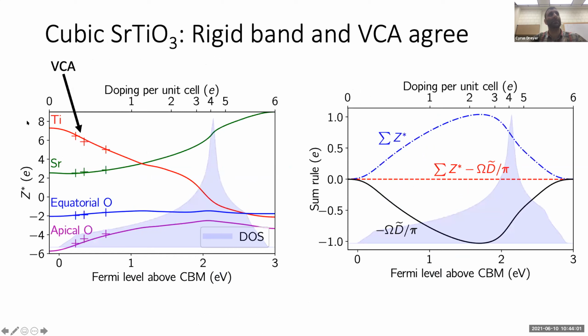So this is the same plot I showed for tin sulfide, Born effective charge versus Fermi level. Here we're doping across the entire T2G band. Of course, in an experiment this would be completely impossible, but just to show the trends across the whole band. And these crosses here are using this virtual crystal approximation.